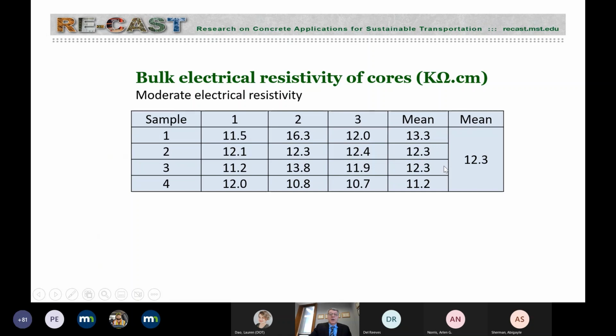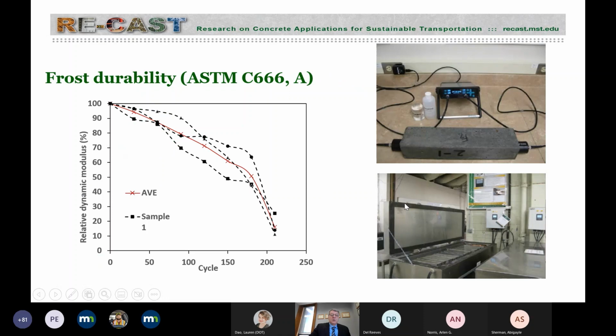We did measure electrical resistivity, not because there's any risk of corrosion, but as an index of transport properties. And the values shown here all indicate moderate electrical resistivity, what you would expect from the mixture proportion that was used. Now, we were interested in freezing and thawing, knowing that the concrete was not air entrained. Still, we were interested in knowing what would be the freezing and thawing.